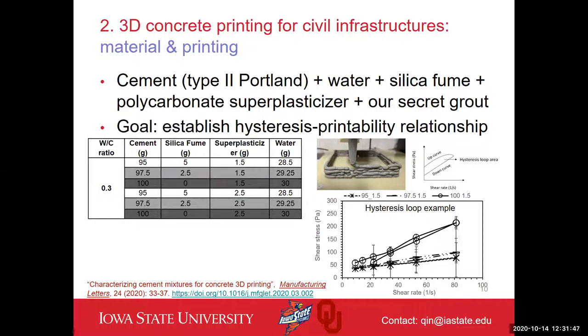What you are seeing is one example of how important the material itself is. For concrete printing, if we do not tune the material properties well enough, we will never get the printing results as we want. It's very difficult, way more complicated than polymer-based printing or metal-based printing, because concrete has a solidification time that is different from polymer and different from metal. Based on our study, we tried to set up a relationship between the rheology property of the cement and the printability. We ran rheology testing of the material, calculated the hysteresis loop area, and set up a correlation between the hysteresis loop area and the printability. This loop area is determined by the combination of the cement, silica fume, the grout we added, and water. So we have some initial findings.